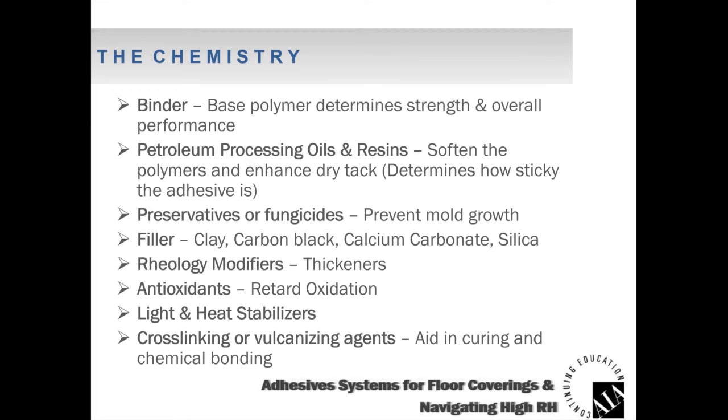In addition to the water that may be in there, you have fillers in there too: clay, carbon black, calcium carbonate, which is basically limestone, and silica, not silica sand, but more like silica fume, a powder material.